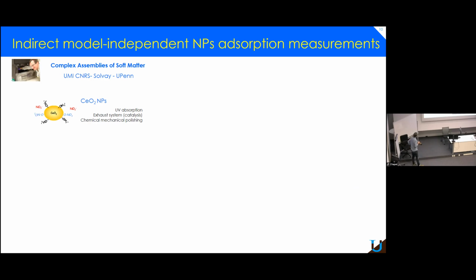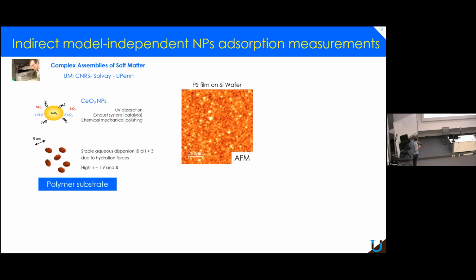And so we had on the shelves this cerium oxide nanoparticle. They were used for UV absorption applications or in exhaust systems because it's a strong catalyst, and also in chemical mechanical polishing. This is typically the way to polish wafers, silicon wafers. They use those guys in fact. And it turned out that I tried to adsorb the solution of those particles onto polymer substrates. And you can see here the adsorption was quite strong.